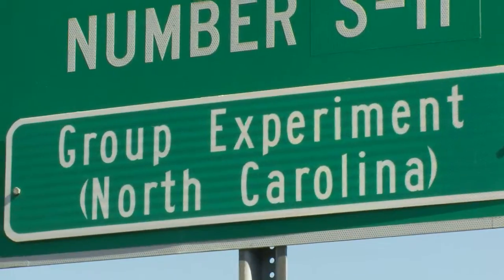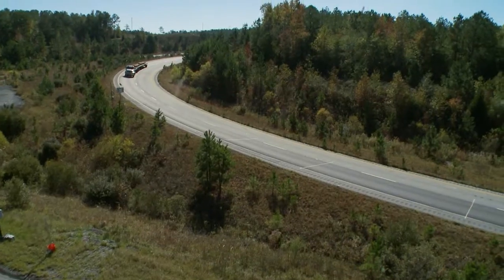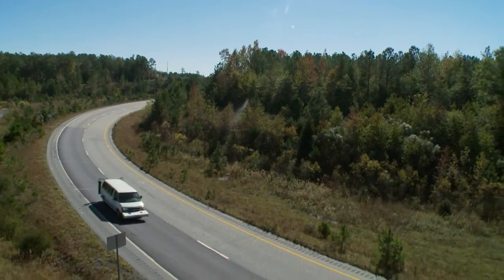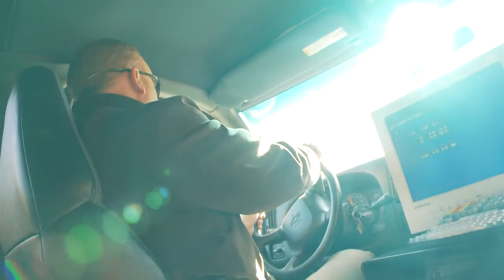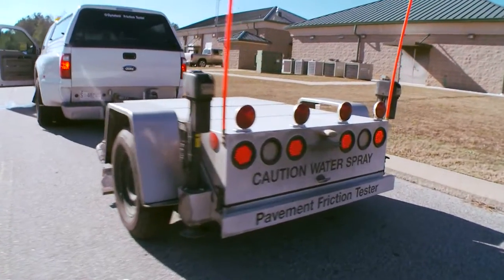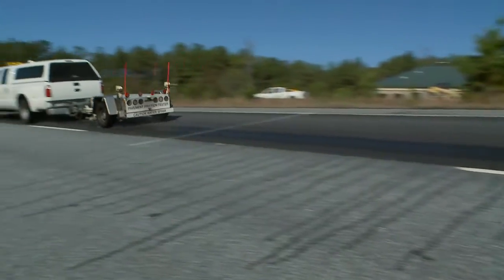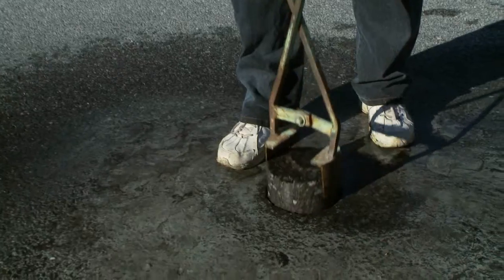In order to accomplish that work, we run a fleet of heavy triple trucks five days a week, Tuesday through Saturday, from approximately 5 in the morning to about 11 o'clock at night. For each section, we measure roughness, rutting, and macro texture every week, and then there are some other tests we run every week, some tests we run monthly — for example, surface friction — and some tests we run quarterly — for example, destructive coring.